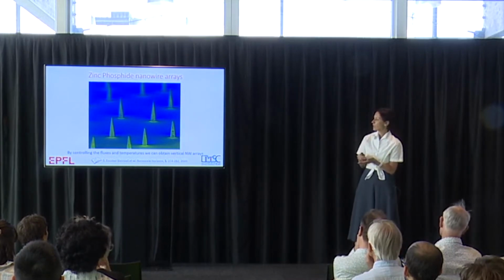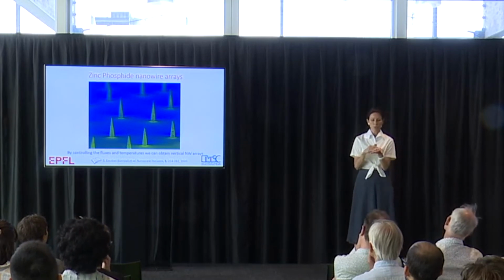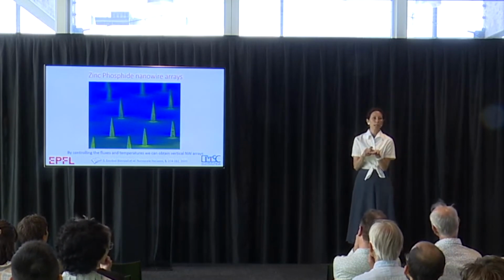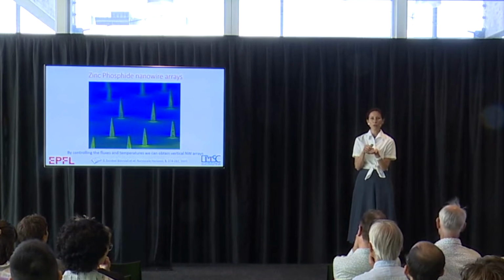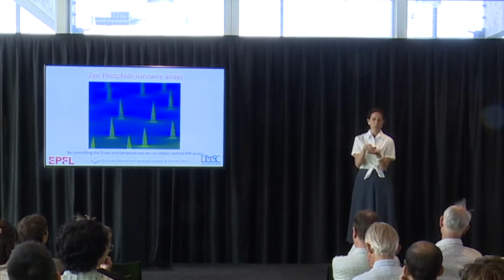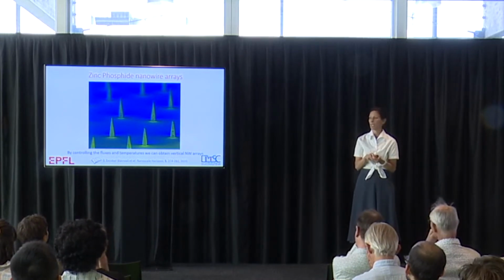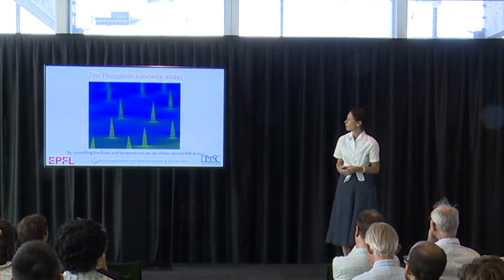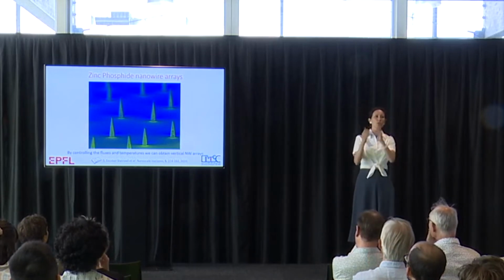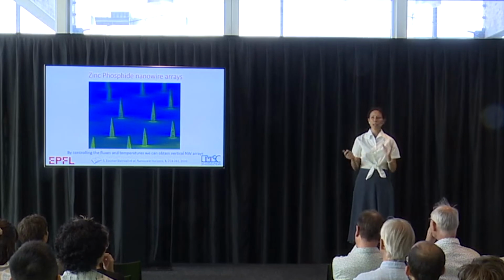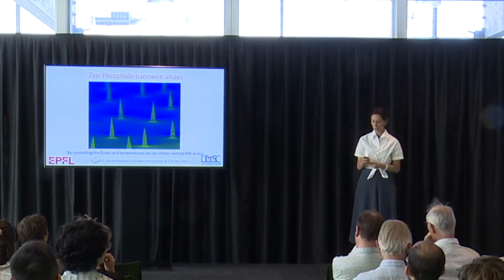So what we did here, Simon, what he did here, he took a substrate, he exposed it to a very soft argon plasma. This creates some defects, and there you would have a nucleation of the nanowires. That's how he did it, and you have this beautiful picture here. You have mainly vertical wires. Depending on the conditions, they can have different shapes also, depending how he does it.